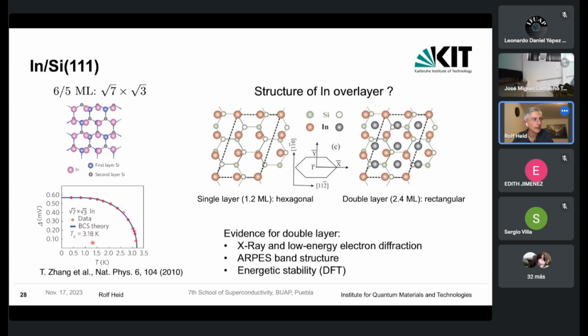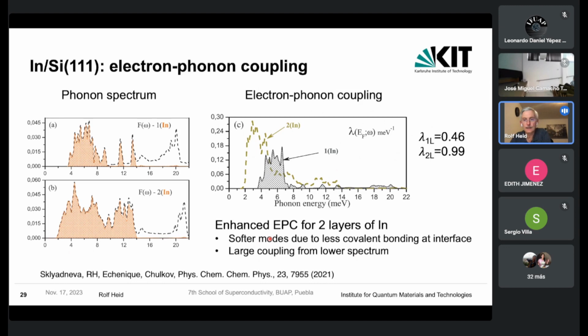There has been later on a discussion in the literature whether one is really dealing with a single atomic layer, and there has also been the proposal that we actually have two layers of indium on top, which have the same type of symmetry and which are responsible for these superconducting properties. We have therefore looked with our computational tools at both of these predicted structures, and did the analysis of the phonon spectrum and the electron-phonon coupling spectral function.